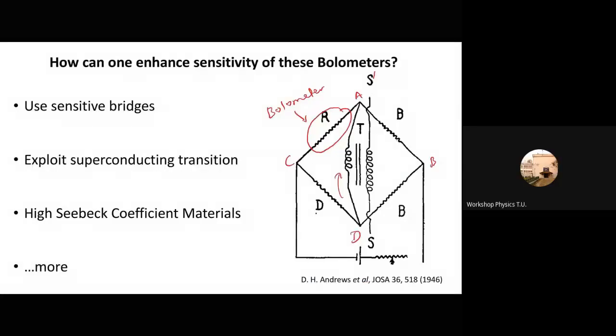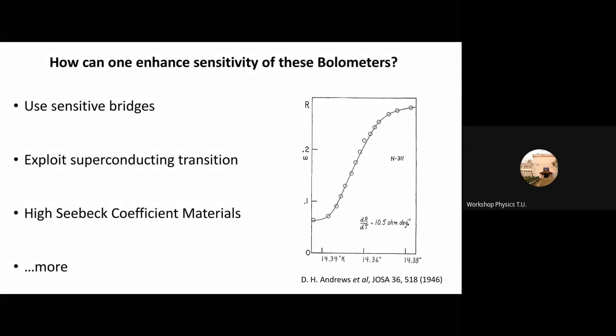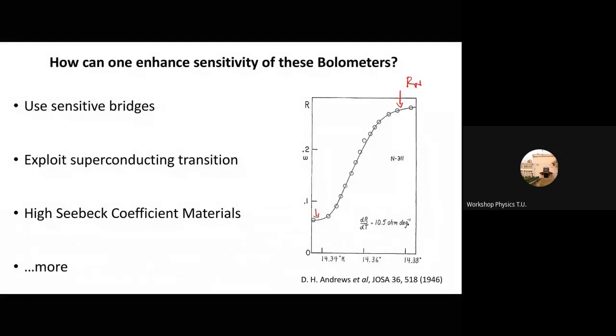Over here, it is important that this resistance change as a function of temperature has a good slope. It is important that the slope of variation of resistance with temperature is as high as possible. And that's where the superconducting transition was initially proposed way back in 1946 as an interesting way of implementing a bolometer. Here a superconductor goes from a normal state resistance to a superconducting state. The non-zero value here is primarily due to the limitation of the voltmeter used, the noise level of the voltmeter used by Andrews et al. So this is essentially the zero resistance state.